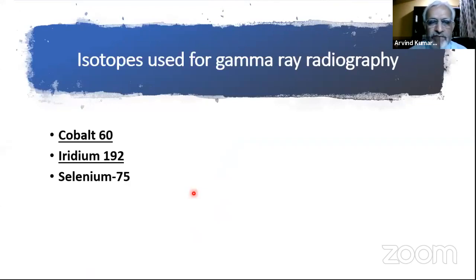For gamma radiography, we generally use three radiation sources, that is natural isotopes, cobalt-60 or iridium-192, or recently, in the last few years, selenium-75 has come, because for lower thicknesses there were sensitivity issues where iridium-192 was being used but not giving the sensitivity. So instead of opting for X-ray, you have in between another option using selenium-75. Selenium-75 gives you sensitivity better than the iridium-192 source and, I would say, a little worse than X-ray.